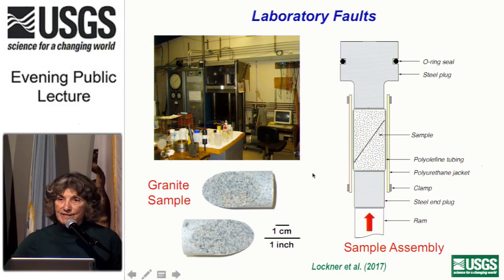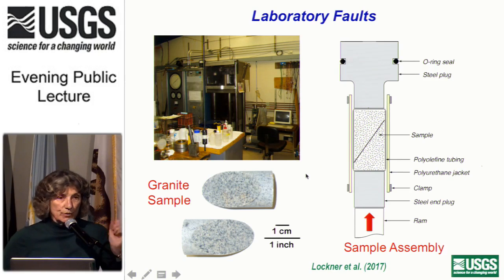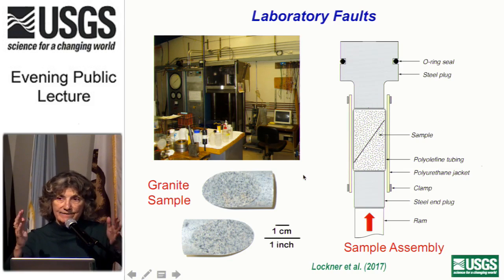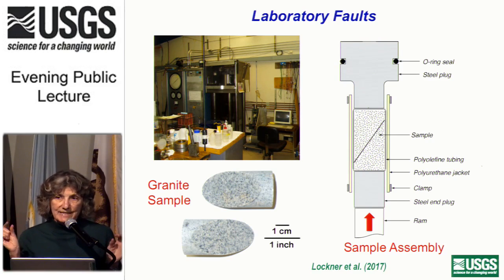So the experiments I'm going to be describing were run at room temperature on room dry samples, but they were conducted at a very high confining pressure, 4,000 bars, 400 megapascals. And the samples failed in what's called stick-slip events. It's a laboratory equivalent of an earthquake. And these stick-slip events are very short and rapid. It took place in about a third of a millisecond. The amount of offset was about an eighth of an inch.